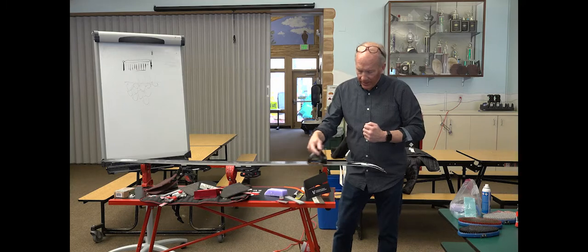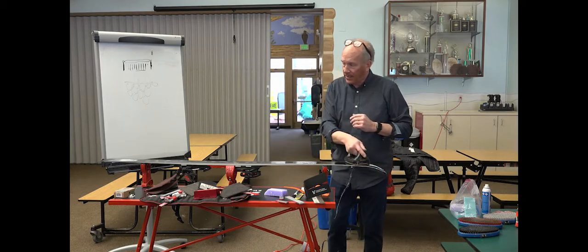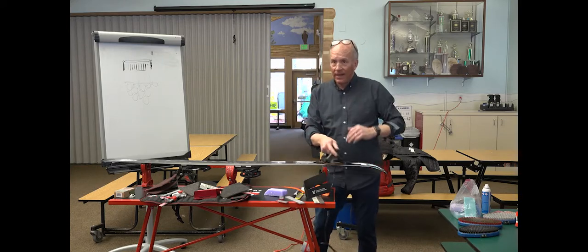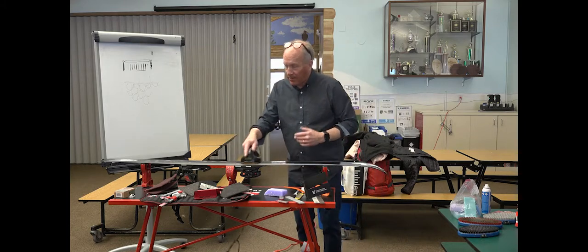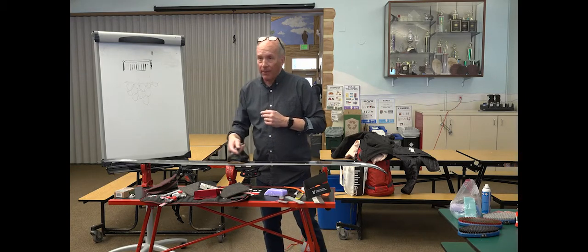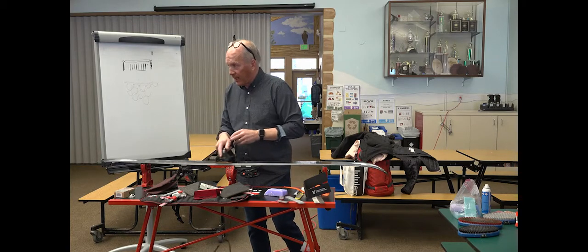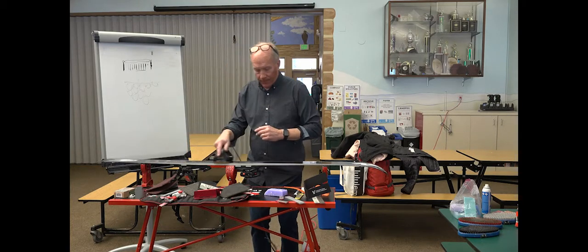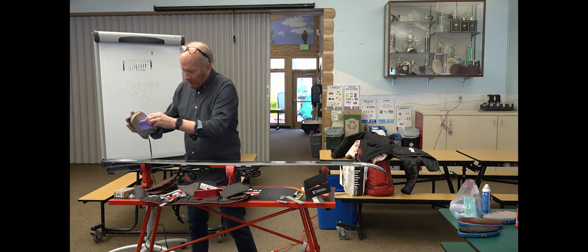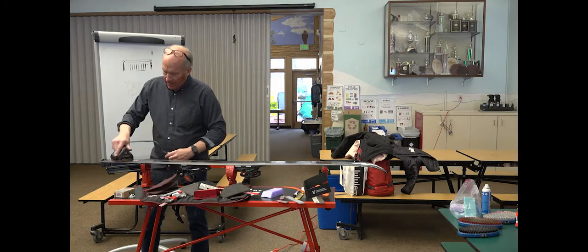But generally, I like to say when the ski goes into reverse camber, you've got enough wax on it. What happens is the ski will actually bow this way. As you heat it up, the materials on the base of the ski are expanding, and so the ski will go into reverse flex. No big deal, it goes right back to normal. That, to me, is the sign that I've gotten enough wax in the base and the wax hot enough. Different waxes have different temperatures. As long as you're making them liquid, that's what you're doing. With a lot of the fluoros, they are pretty temperature specific. They do make irons with electronic thermostats on them, but for our purposes, this is good enough. More on there. So you want a good coating on the ski. Tip to tail.